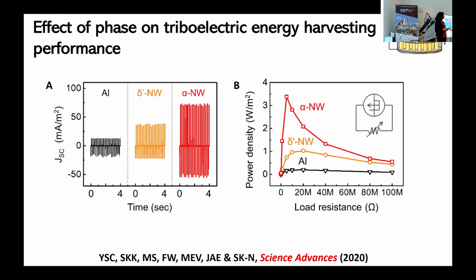And this was surprising to us because we thought, well, the alpha nanowires were not of much use from a piezoelectric point of view, but they work really well, in particular in the nanowire form, because they do have a dipole, and this dipole is very strongly bound due to the strong hydrogen bonding between the sheets. And because we have this alignment within the nanowires, it's always pointing in the right direction. You don't see this in films, because in films you have different lamellae. Each lamella will have a dipole moment, but they're pointing in different directions. So the net effect is nothing.